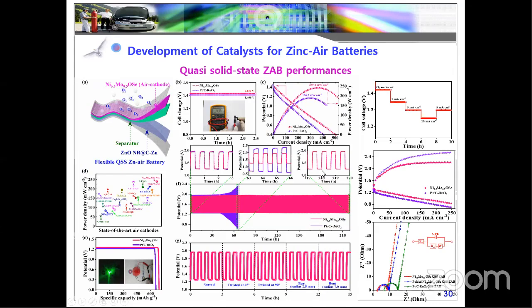You can see the first and final stage, the round trip efficiency almost retains, because this is the cathodic part and this is the anodic part. In the case of platinum and ruthenium based catalysts, the potential increases due to corrosive effects, carbon corrosion and dissolution of the active materials.